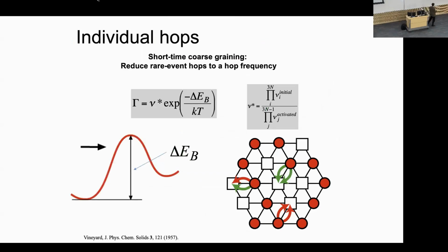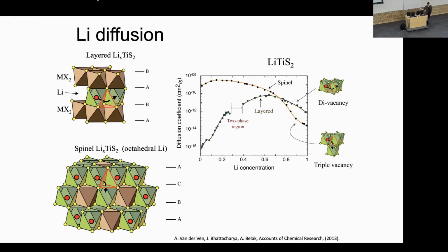You can construct kinetic Monte Carlo with transition state theory for the individual hops. But the problem with these individual hops is that in a disordered system, like a battery material, these barriers are going to depend on the local environment. So depending on where you are, this barrier will be different. And so again, you have to use these cluster expansion techniques to parameterize the dependence of these barriers on the local environment. And then you can go to kinetic Monte Carlo and calculate diffusion coefficients.